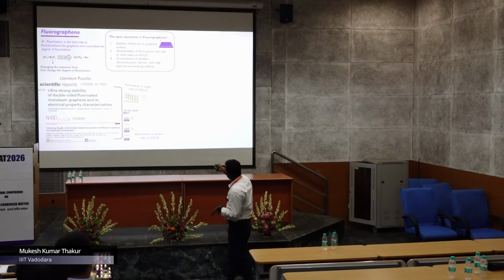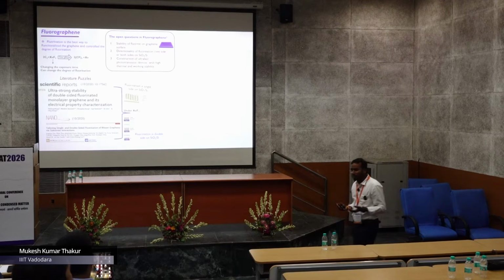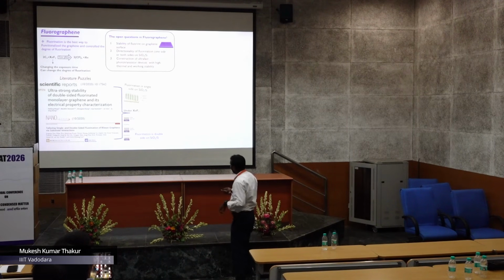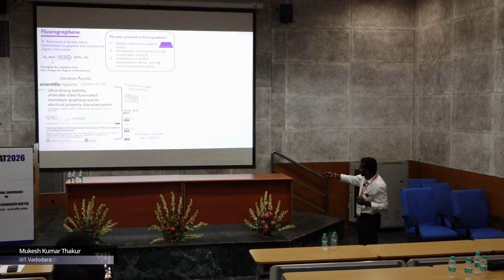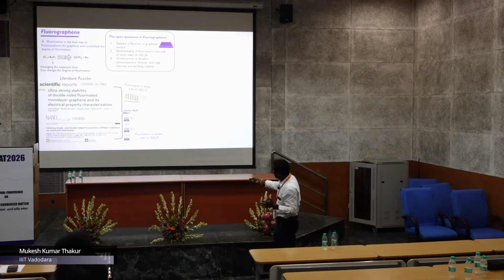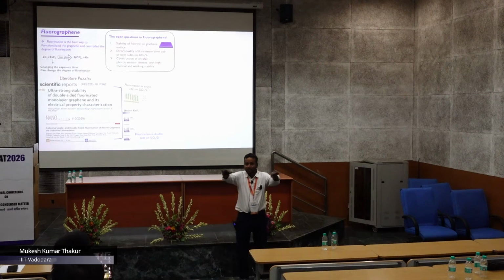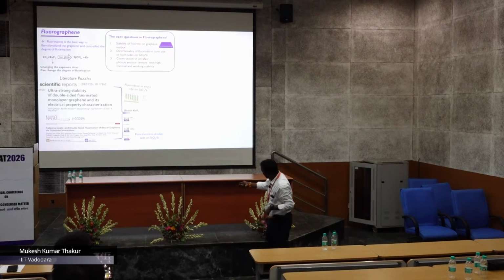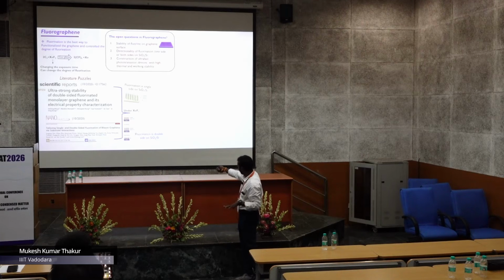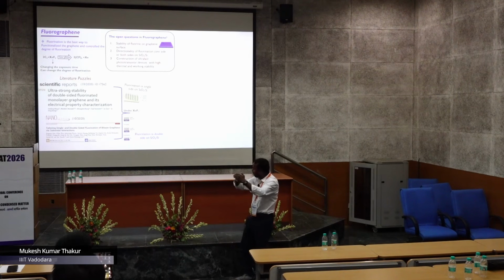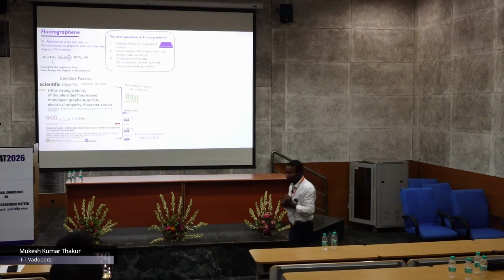Then there are open questions out there, like stability, how stable this is. Also, when you make fluorinated graphene, you lose the mobility and the optical absorption and lots of things. And then there are these two reports, as Professor Soni was also discussing, with some contradiction, right? Both came within a week of each other. One says that when you do the fluorination of monolayer graphene using this technique, you have only single-side fluorination, the top. The other says no, it's not true. When you have the same graphene on silicon/silica, the substrate being the same, you have both-side fluorination, top and also bottom. So then I came into the picture: let's check, this is a good opportunity to know whether it's true or not.